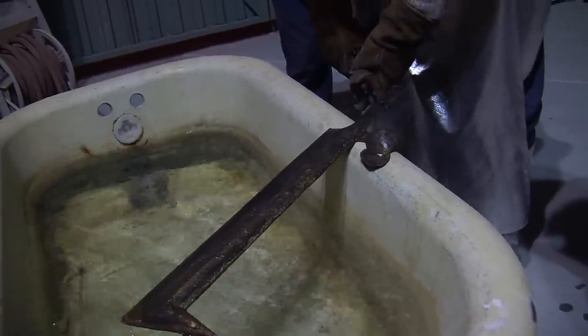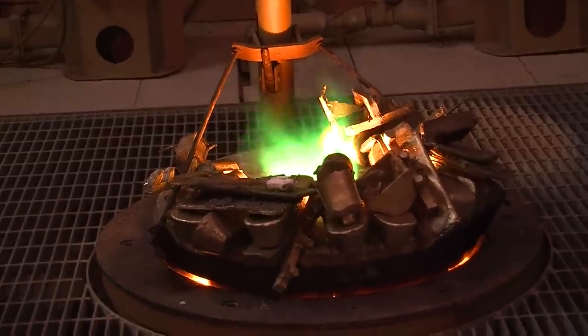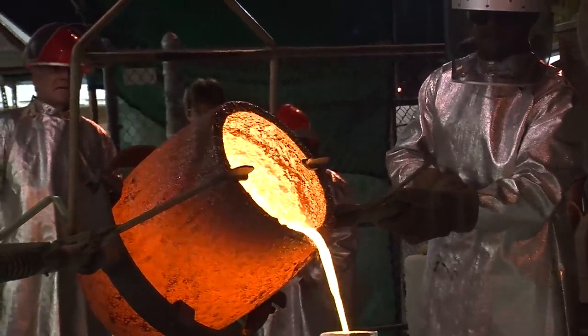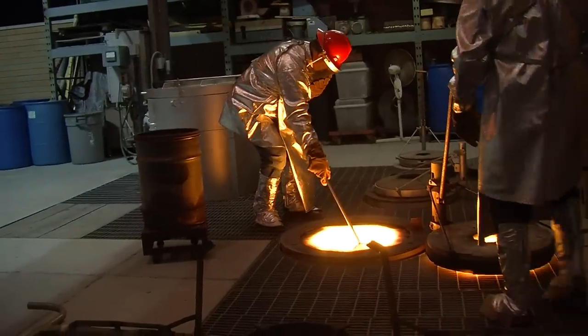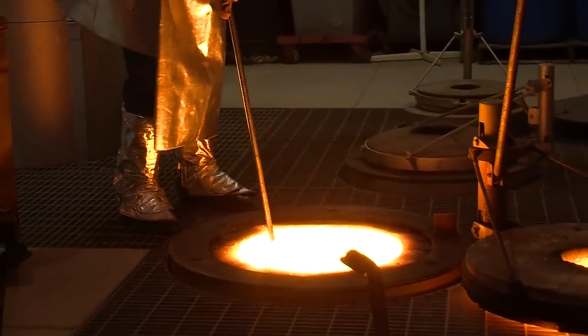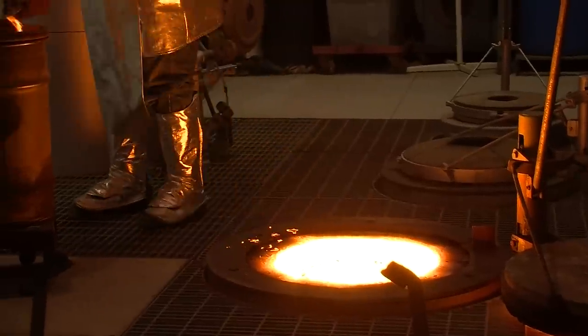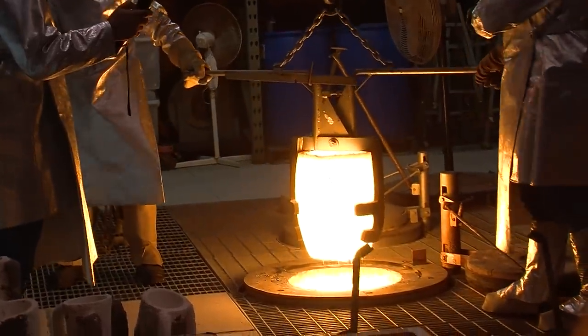It will soon be a sword. Bronze costs about $8 a pound and requires such intense heat that anyone working with the molten alloy has to wear the same protective gear as a firefighter. We use a MIFCO furnace — it is a very high-tech, high-velocity furnace, runs at about 1.2 million BTUs, and we take it up to about 2,300 degrees to melt the bronze, and then we pull the crucible out, which is the container that the bronze goes into.